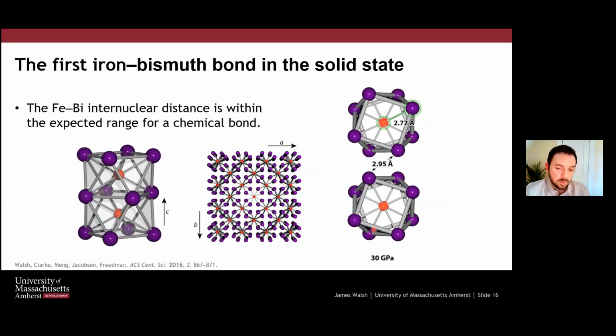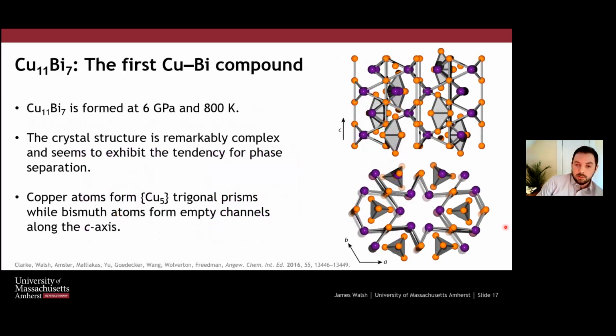And so you can see that at 30 GPa, this interaction between the iron and bismuth is 2.72, which is within the expected bonding radius for this structure type. And so we've made this intimately bonded compound in a system that, until that point, didn't seem to be reactive. And so that was exciting and made possible by the beamline and support from CDAC. Otherwise, I'd have been trying nanoparticles still probably. Okay, so another system that we investigated was the copper bismuth system.